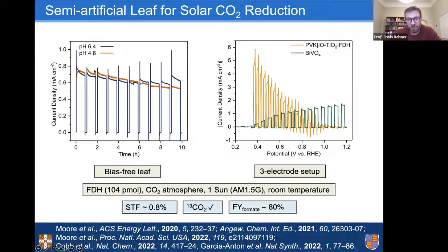And at the same time, what I think is the most exciting is that this becomes a completely selective system. We're really only producing formate, with a Faraday yield here of 80%, but this is just analytics, and we cannot identify any hydrogen or other side products. So we are not co-producing hydrogen. And the higher current density also translates into a solar fuel conversion efficiency of 0.8%.